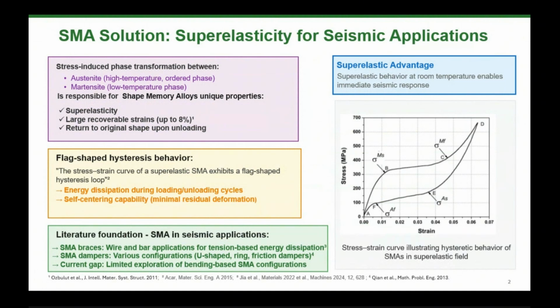This transformation of phase under stress makes this alloy have this flag-shaped hysteresis behavior when subject to stress. And thanks to this kind of curve, they have the ability to dissipate energy during the loading and unloading, and to have self-centering capability, because we have minimal residual deformation after the stress-strain cycle.